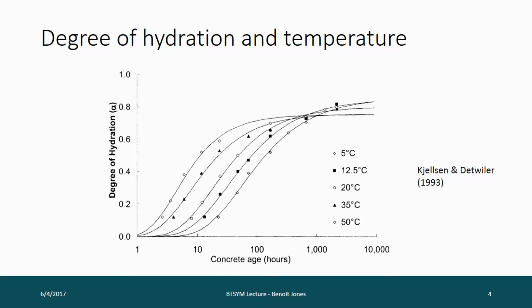One thing to notice is that around several hundred hours, the curves actually cross over. So this idea of being able to take account of temperature works fine, but it doesn't quite work in the very mature ages. And that's because crystal formation is slightly affected by the actual temperature.